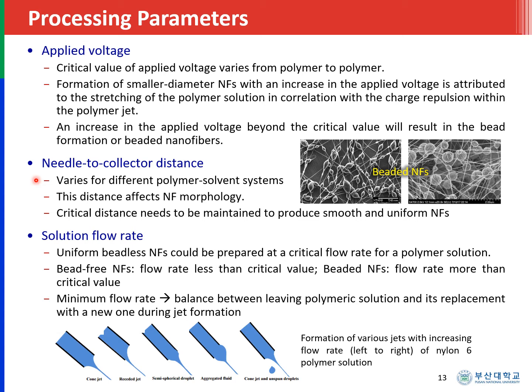A critical distance for a particular polymer solvent system should be maintained to produce smooth and uniform nanofibers. If that critical distance is not maintained, or you don't know that critical distance, then you will end up with beaded nanofibers, or you will not produce nanofibers at all. Third one is solution flow rate.